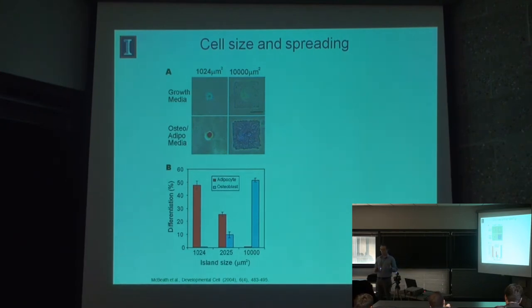Basically, when they first started calling these mesenchymal stem cells, they showed that if you seed them at low density on tissue culture plastic, and then at high density on tissue culture plastic, the cells that were initially seeded at low density after several weeks showed a much higher degree of bone cell differentiation. And no one was really clear why that was.